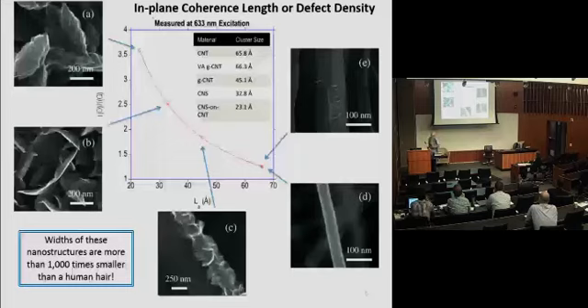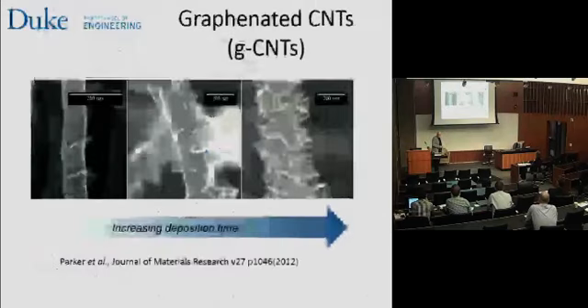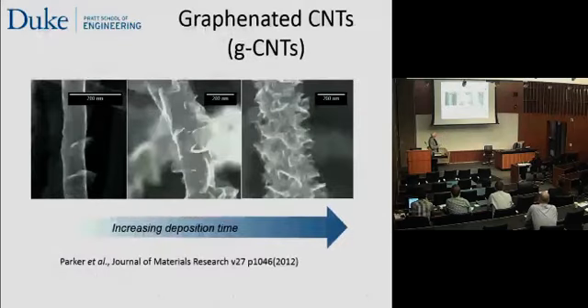And so we go from sort of these materials that look very smooth, these nanotubes, all the way up to these flakes that have lots of edges. And we have a whole array of morphologies in between. Depending on what we want to do with these materials, we choose different morphologies. Keep in mind that these are all nanostructures, so this carbon nanotube is about 1,000 to 10,000 times smaller than the human hair. So we're talking about very small structures that can interact with electrolytes and with charged particles very differently than a macromaterial. So this material that I mentioned before, graphenated carbon nanotubes, is shown here.